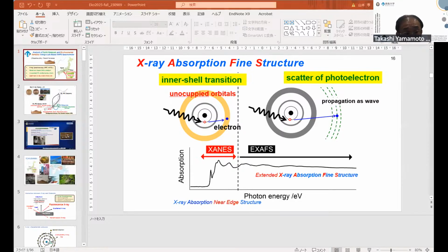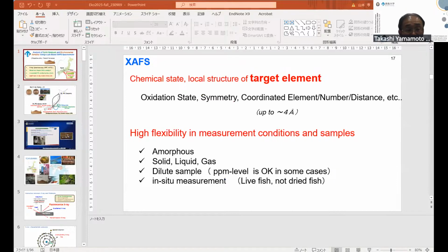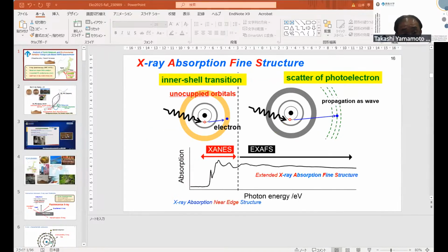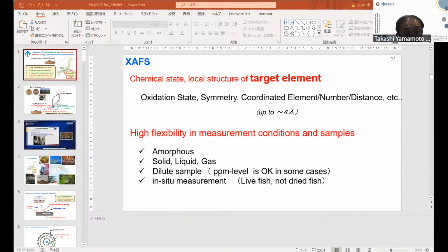This is due to inner shell transitions or scattering of photoelectrons. The same spectrum, but different phenomena occur in this spectrum. Thus we can obtain information about the target element. This is because the absorption edge depends on the element and shell. By choosing the energies, we can select the element, and then we can know the information about the target element.